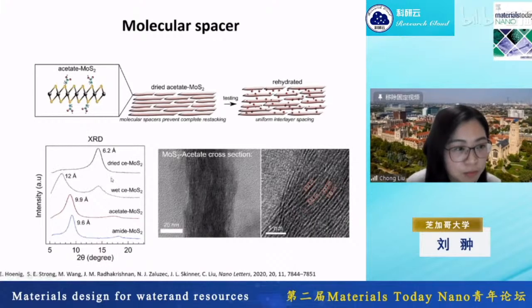You can see that after functionalization with the small molecule, when you dry up the membrane, even though there's no water in between the layers, you get a layer spacing that's much wider than the pristine bulk form, which is 6 Angstrom or even larger than the original lattice spacing. And you can also see that from the cross-section TEM.